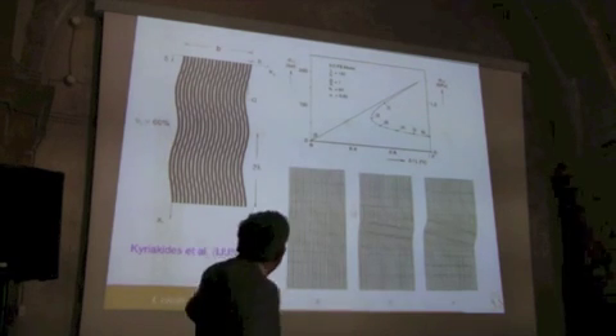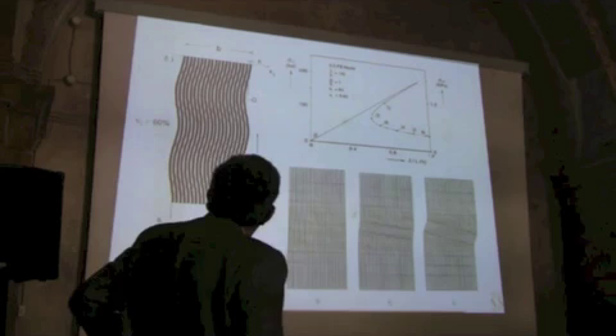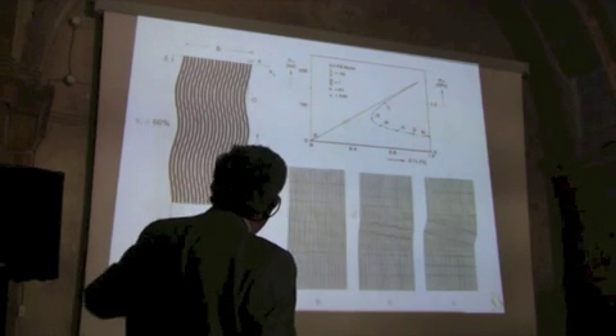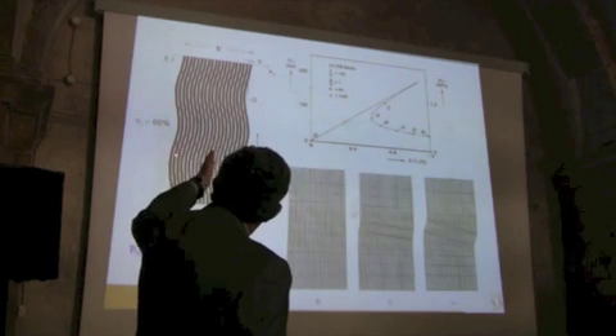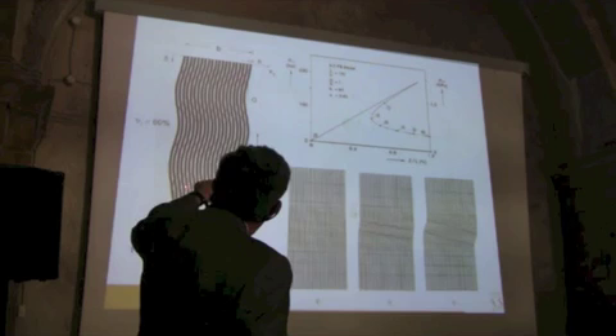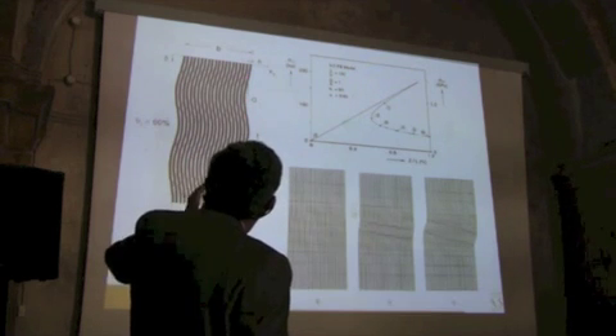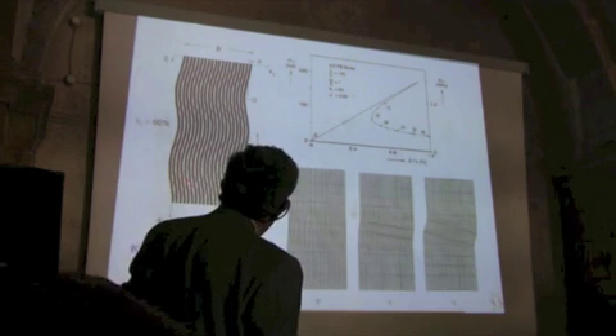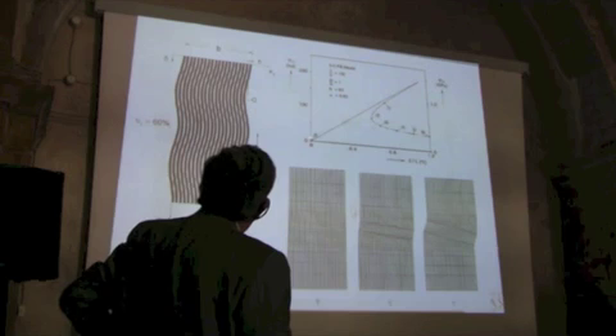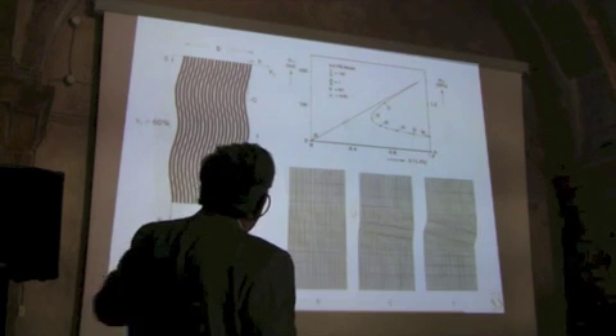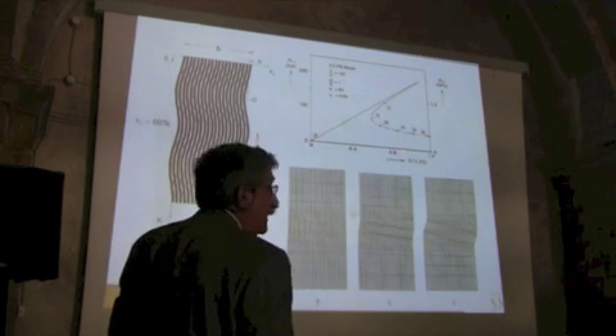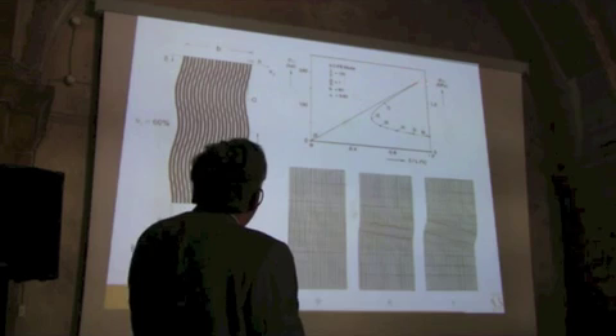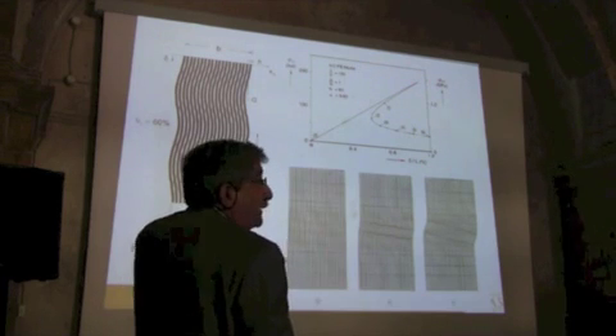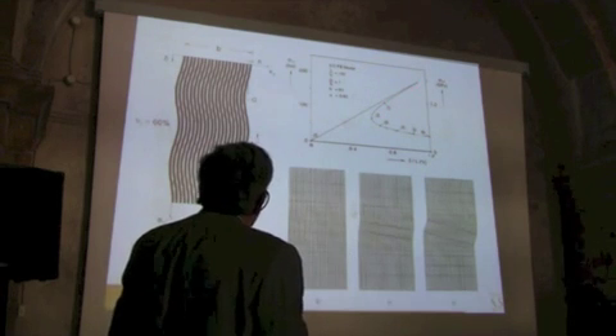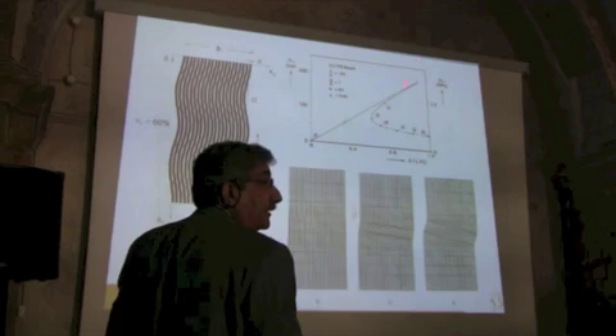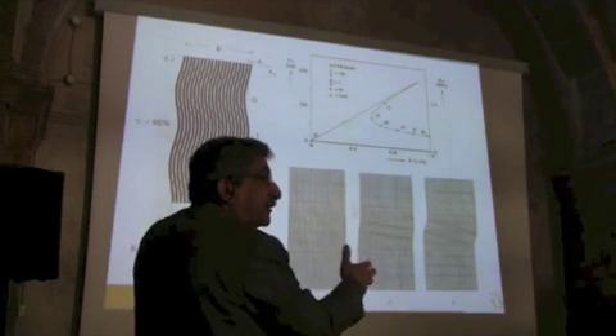Regarding the onset of failure, this is a model that we did in the mid-90s, where we have fibers. It's a 2D version, there is a 3D one also. Fibers that are elastic and a matrix that is elastoplastic. We have put a waviness as an imperfection, and we compress it. If you compress it, this is what you get. Stress, this is shortening. I don't know if you're used to instabilities, but this is as bad as instabilities get. Okay? You reach this point, and you are either controlling the load or you're controlling the displacement in any physical situation. And so whatever you're controlling, this guy is going to jump here. Okay? And that's why the first failure is catastrophic.